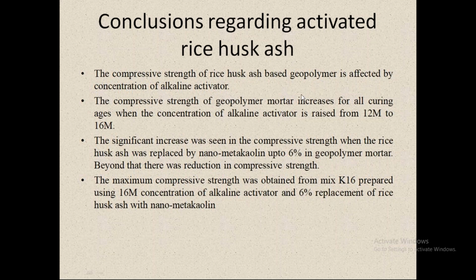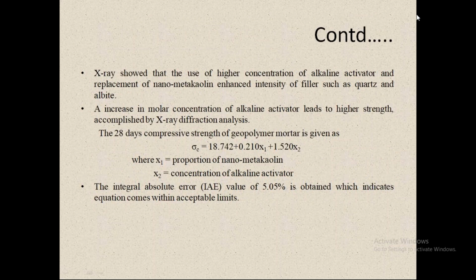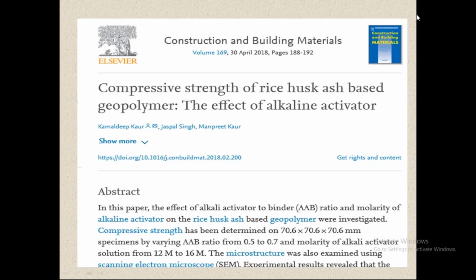There is a significant increase in the compressive strength when the rice husk ash was replaced by nano-metakaolin up to 6% in geopolymer mortar. Beyond that, there was a reduction in compressive strength. The maximum compressive strength was obtained from mix K16 prepared using 16M concentration. So again, the XRD equation was found, and the integral absolute error was determined. This is again, because it was the latest thing, the alkaline activator is a new thing. It has come only during the last 2 years.